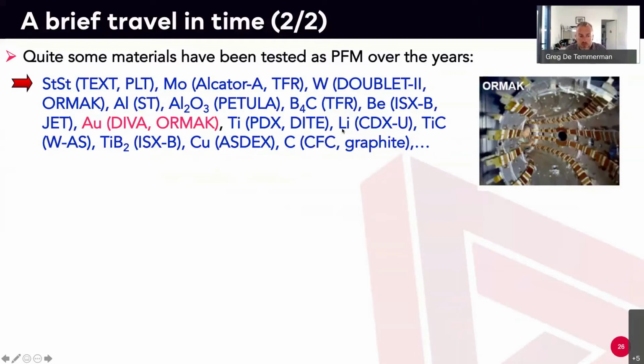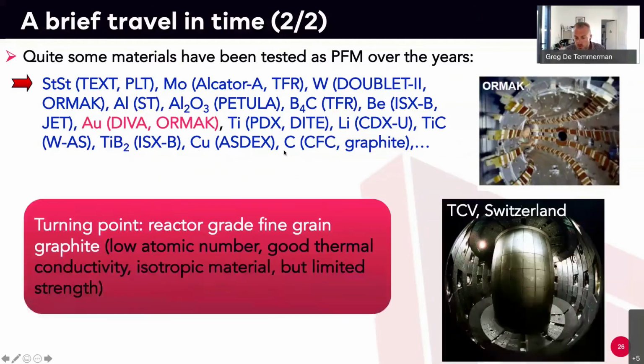Titanium, lithium were used, titanium carbide, titanium diboride, copper, carbon. And actually carbon was a turning point, a revolution for fusion. What happened at some point is that reactor grade, fine grain graphite became available. Carbon is very good because it has a low atomic number. It has a very good thermal conductivity. It's isotropic when you use it in the form of fine grain graphite. It has a limited strength, but we can do with that. But most importantly for fusion, it doesn't melt.